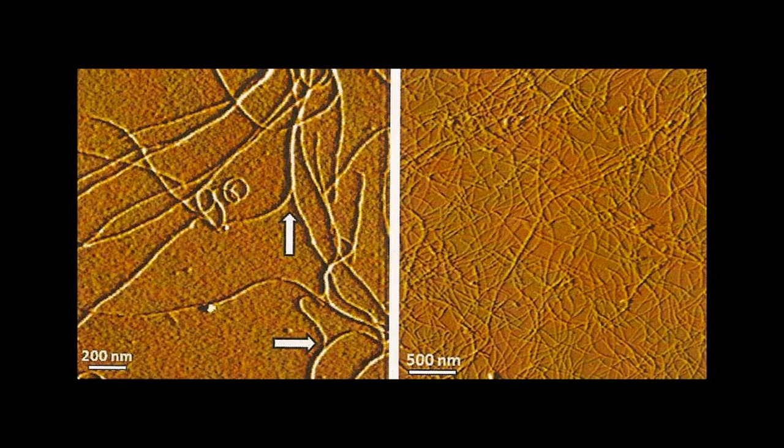They grow, so the image on the left is an early phase image. It was after about 3 or 4 days that the protein fibers were beginning to form. They continue to form for several days, and the image on the right was taken at about 15 days. At 15 days, there are so many fibers that have formed that they settle towards the bottom of the test tube and begin to form these fibrous mats. Fundamentally, we're interested in trying to understand this process, trying to develop an analytical model where we can describe, for a given protein, how it will form fibers in this manner.